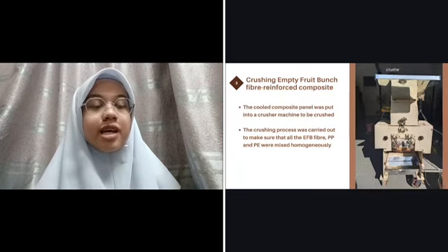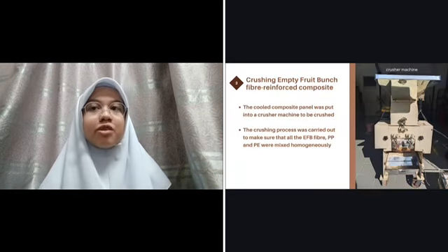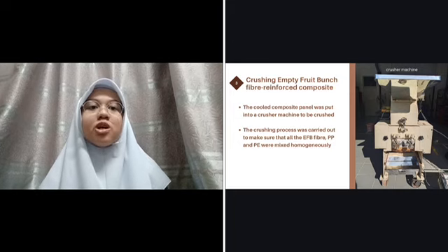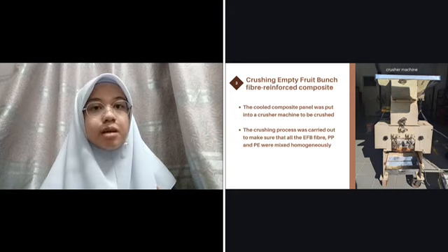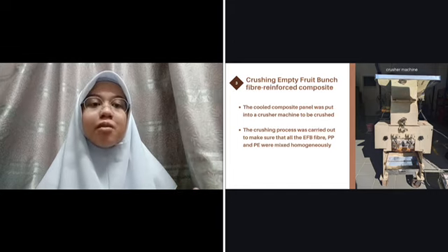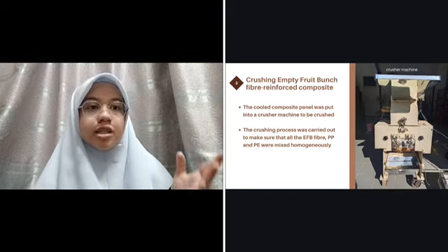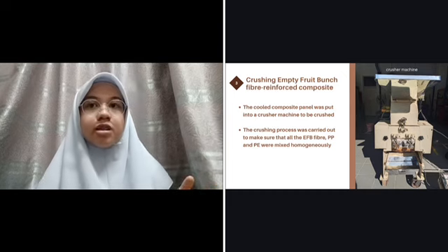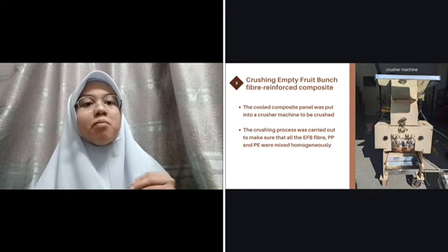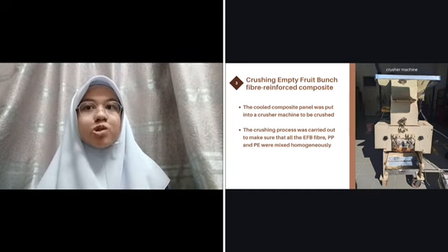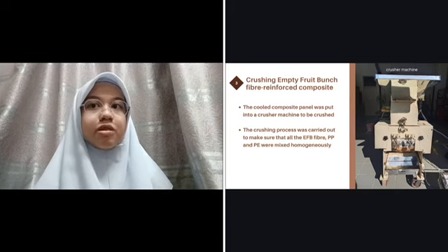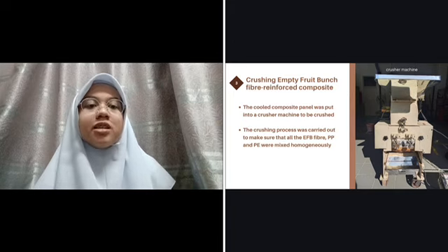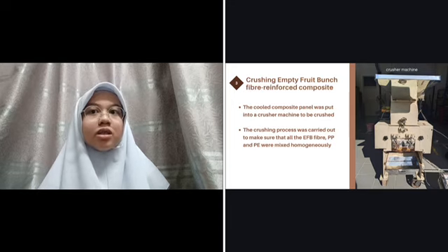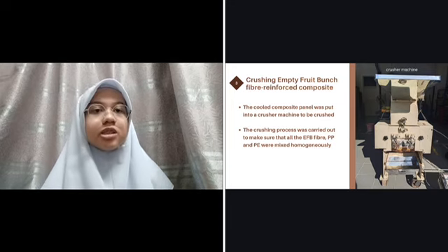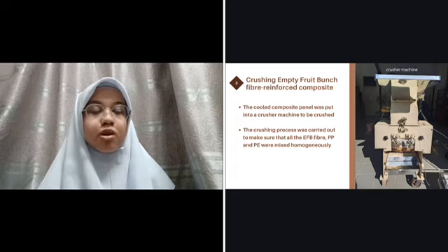Okay, so the third step is to crush the empty fruit bunch fiber reinforced composite, which we produced in the steps before. For this step, we use a crusher machine as shown in the picture on the right. The composite that was cooled before was put into the crusher machine to be crushed. This step was done to ensure that all the materials, which are empty fruit bunch fiber, polypropylene, and polyethylene, were mixed homogeneously.